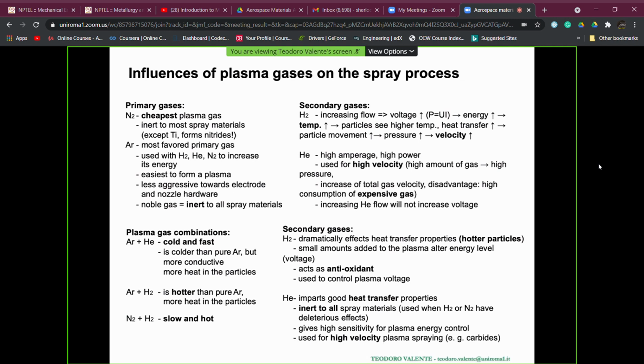Argon, instead, is the most favored primary gas. It is used, let's have a reminder of the energy diagram picture that we have seen, usually in combination with hydrogen or with helium or with nitrogen, just to increase the energy of the plasma plume. It is quite easy to be ionized, so it's quite easy to form a plasma by using argon. It's an inert gas, so it's less aggressive towards the electrodes and the nozzle. And this applies for argon as well as for all noble gas. It is inert to all spray materials, not giving rise to chemical reaction inside the plume.